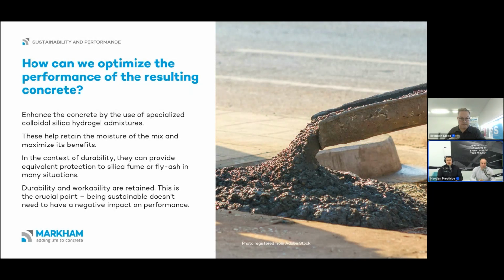And then the third option that we can look at is specialized admixtures. The hydrogel admixtures are the ones that we specialize in, and that is to get these SCM concretes behaving more like a GP concrete. So this is in terms of how they place on site, the workability. We've done a lot of concrete where it's pumping nicely, it's placing nicely. You're not getting that late bleed out of the concrete. It's more like a standard concrete in that respect.